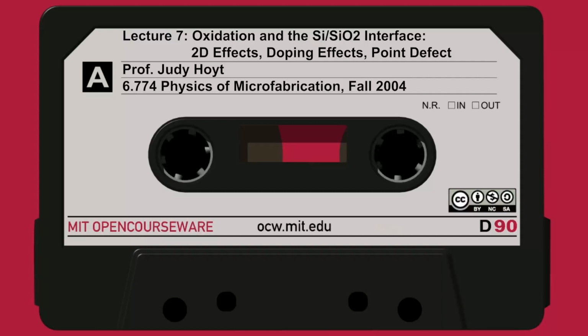Now, of course, it's said that on the flat regions he was growing 5,000 angstroms. So that's not particularly thin. So depending on the temperature at which he was growing that out, you probably don't expect a huge effect in his results from crystal orientation. But nevertheless, you have to take into account if you're oxidizing a trench and you're growing a very thin oxide, the orientation will impact the rate. We saw that last time.